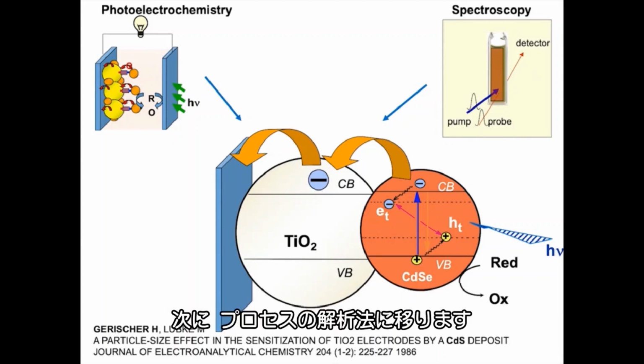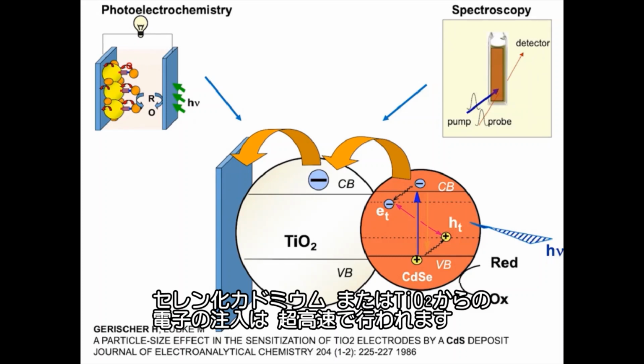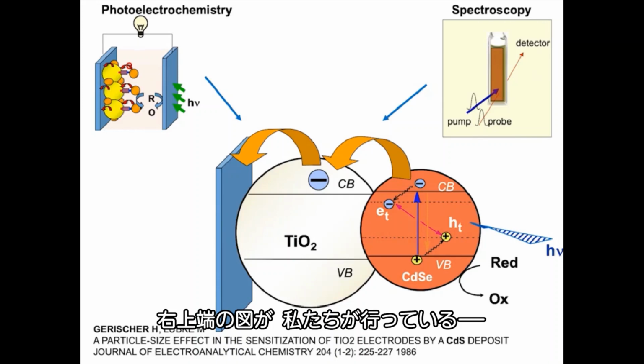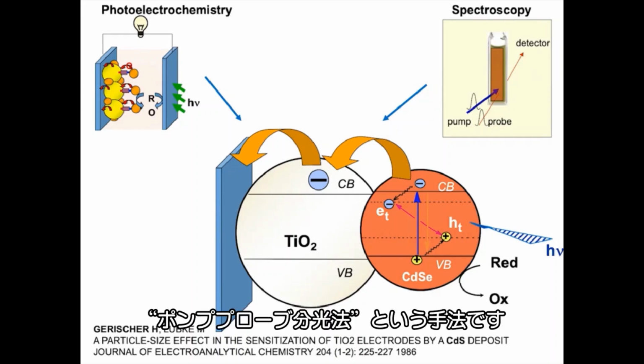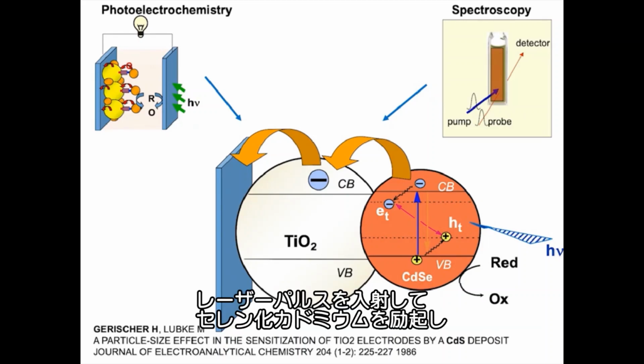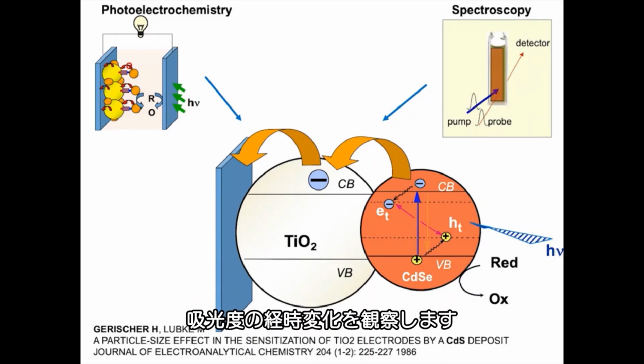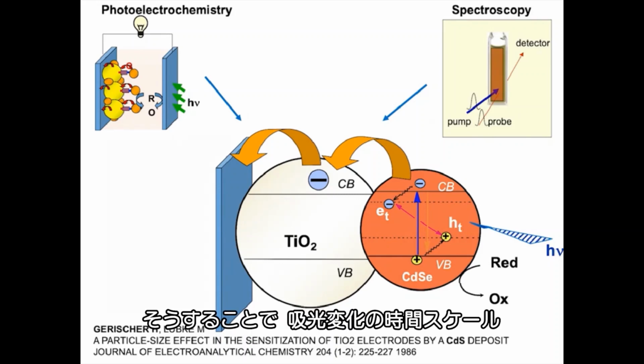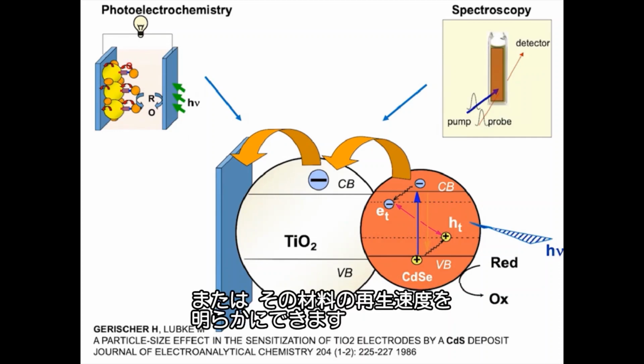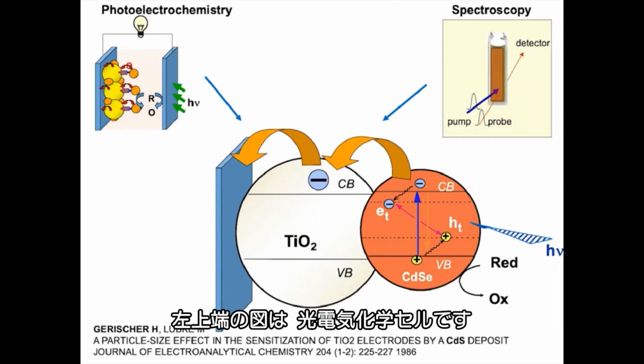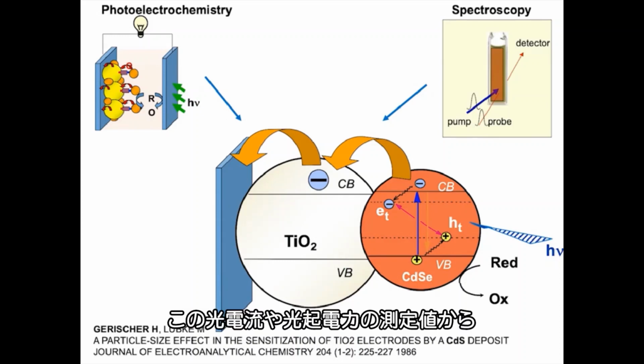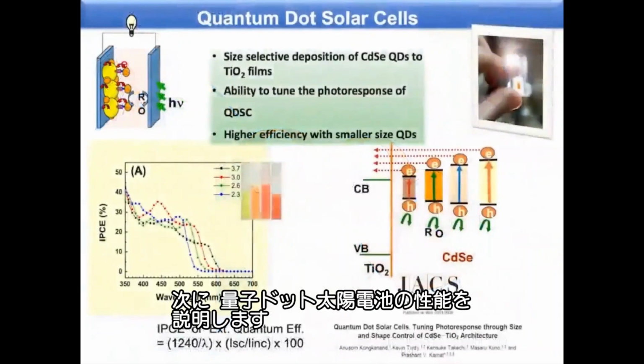Now how do you see these processes? The injection of electrons from cadmium selenide to TiO2 is an ultra-fast process. On the top right corner we show you a method that we use. We call it pump probe spectroscopy, where we bring in a laser pulse to excite this cadmium selenide and try to see the changes in the absorbance with time, and that gives you a time scale of how this absorption changes, or how the material is restored, and at what rate. The top left corner shows a photoelectrochemical cell, where we can study photocurrent and photovoltage measurements to study overall efficiency. In the next slide you will see the performance of a quantum dot solar cell.